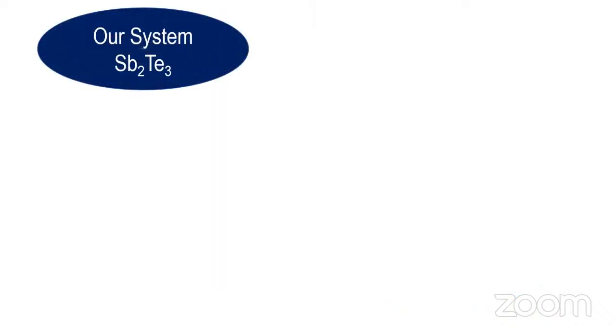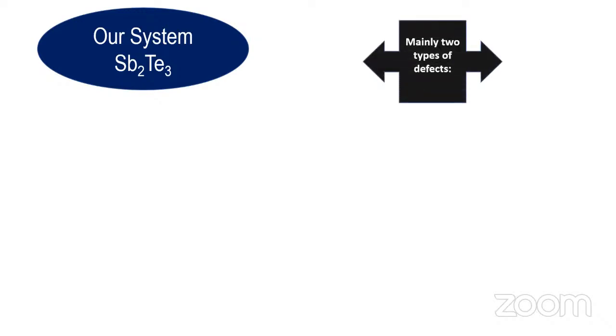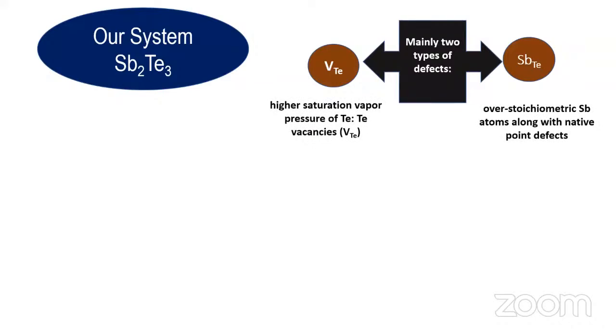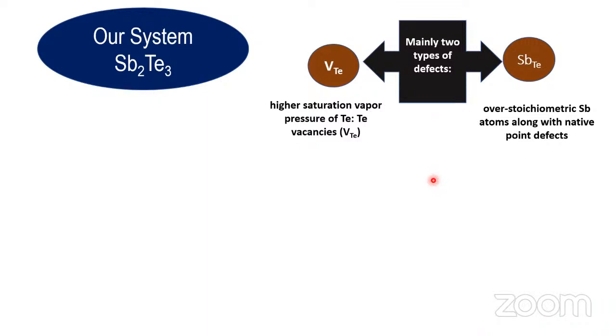We chose our system Sb2Te3, antimony telluride, which gives very satisfactory thermoelectric performance at room temperature due to its narrow band gap and its inherent defects. Its inherent defects are mainly of two types, tellurium vacancy and SbTe anti-site defects. Tellurium vacancy is created due to the higher saturation vapor pressure of tellurium. And as tellurium evaporates, Sb goes to tellurium sites and creates native point defects.